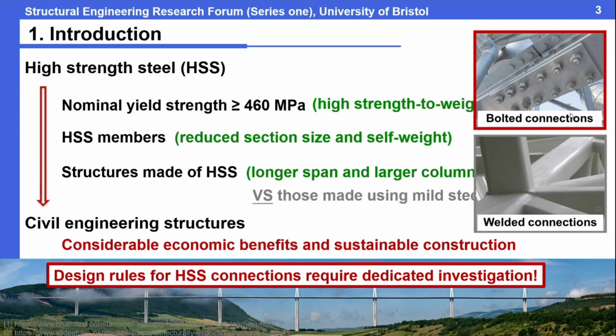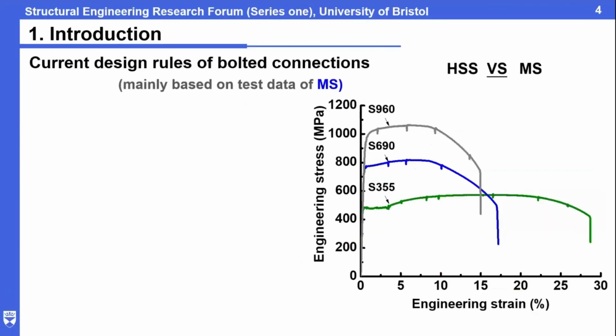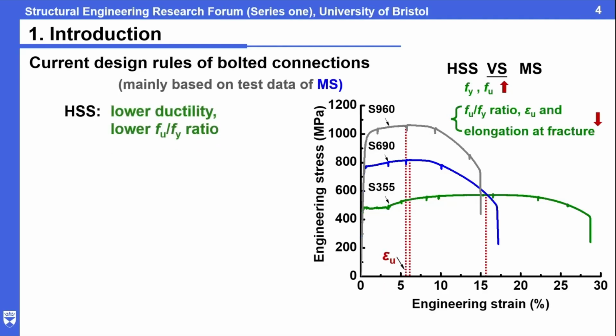So let's see the current design method for the bolted connection. The current design rule of the bolted connection from Eurocode is mainly based on the test data from mild steel bolted connections. As shown here, you can see the stress-strain curves from tests comparing high strength steel with mild steel. You will see, of course, the yield strength and tensile strength are larger. However, the ratio of tensile strength to yield strength and the ultimate strain are relatively lower. It means the ductility of the high strength steel is relatively lower compared with mild steel.